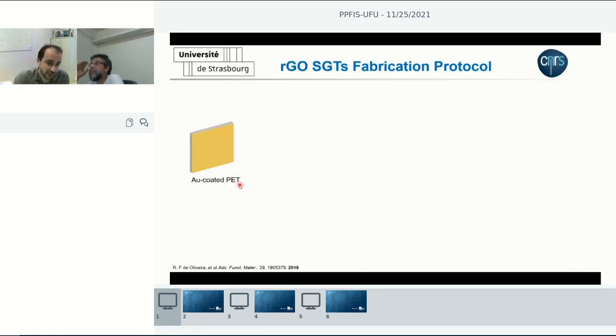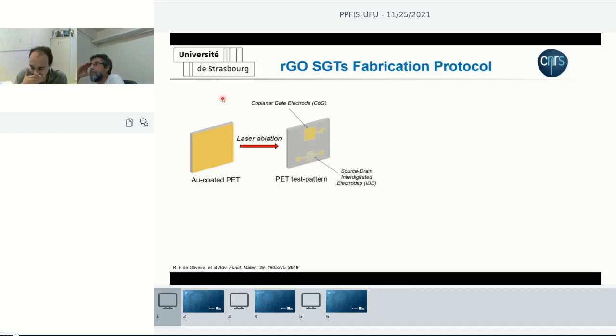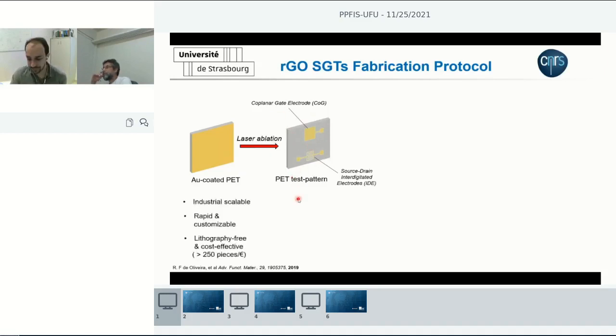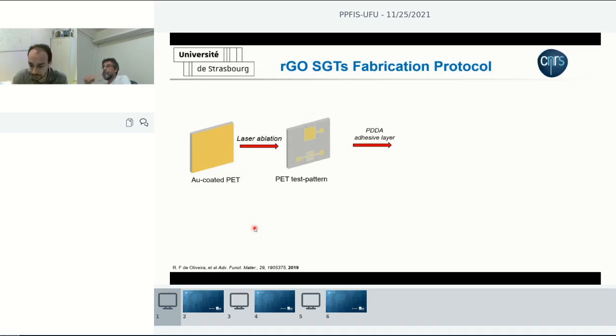We fabricate solution gate transistors of reduced graphene oxide on plastic. We started from a gold-coated plastic foil, where we create the electrodes with the assistance of a laser via a laser ablation method. So we remove the gold from the places that we do not want. In this case, we fabricate a coplanar gate architecture. Its advantages are it's industry scalable, can be customizable with the laser. You can pattern whatever structure you want. It's also fast. It does not involve lithography or the use of a clean room, and you can produce hundreds of pieces per dollar or per euro.